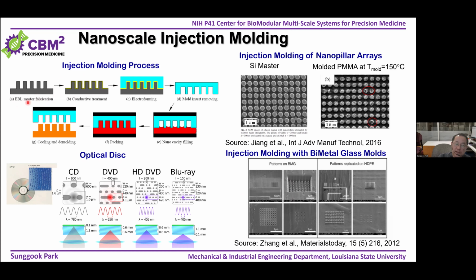But after fabrication of the master mold, you need to replicate it into a durable metal stamp using an electroforming process. But this process takes a really long time. Normally it takes about a week to electroplate with very good replication fidelity for the nanoscale. Which means the initial tool cost is very, very high compared to nanoimprint lithography. So most people just develop prototype devices using nanoimprint lithography, and they have to separately develop a scalable fabrication technique like injection molding.